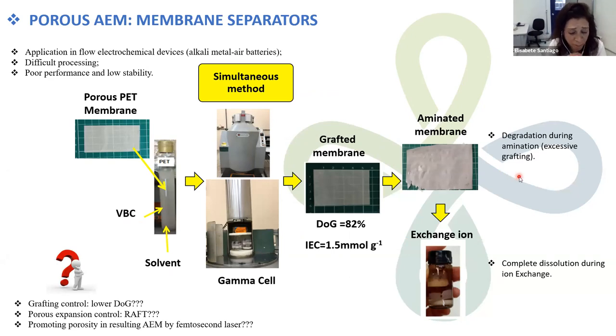We are also working on porous AEM, aiming at application in batteries and flow electrochemical reactors. In these cases, the pores facilitate the fluid to drain more easily. So you can use it, but you have problems with using porous membranes because you need a commercial porous polymer film. And in this case, the just one we got was porous PET. PET is very hard to work with radiation. So it's very difficult to introduce grafts in PET membranes.